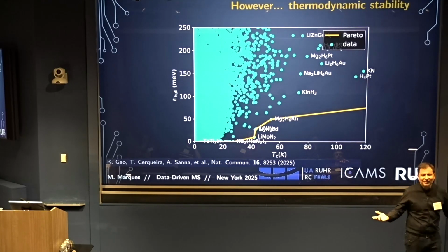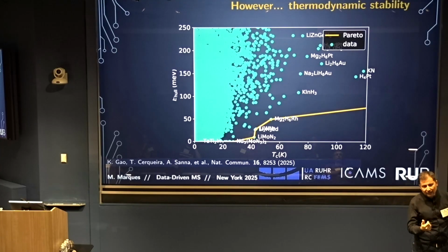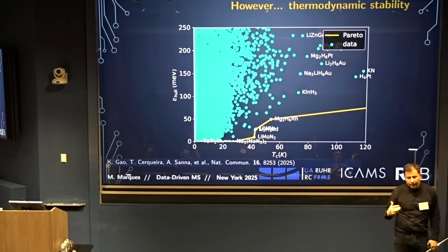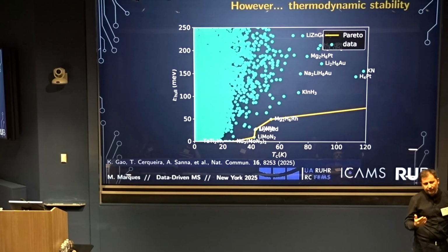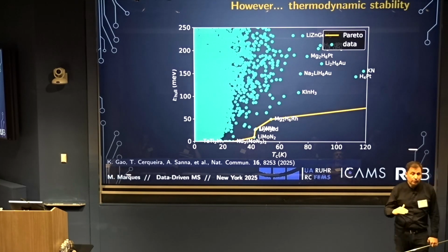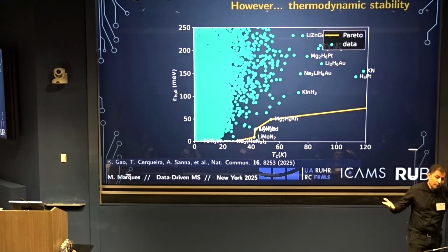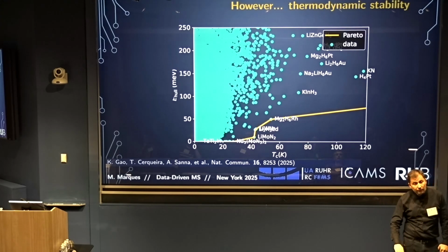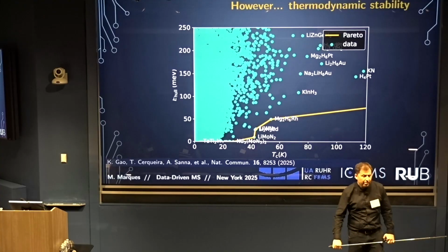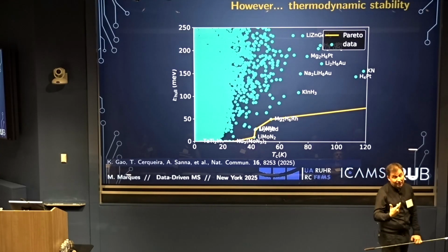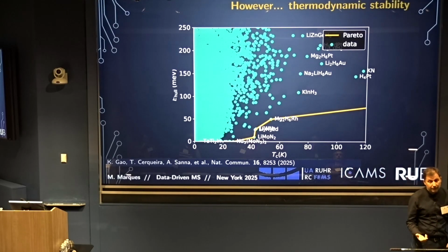They will leave. So it would have to be relatively low pressure, let's say 10, 20 gigapascal. Most of the hydrides that are still stable in these conditions are insulating, which is also what we would expect. I found one, this rubidium phosphorus hydride, that seems to be stabilized, and it needs anharmonicity to be stabilized. Maybe there are more.